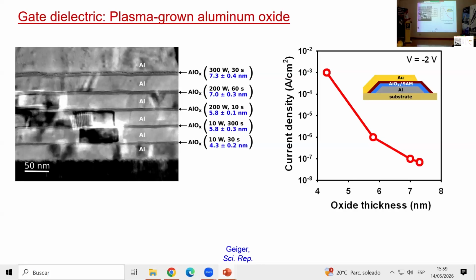That's correct. So what we do is we have to calibrate. So the main parameters for the oxidation process are the plasma power, which we can tune anywhere from 10 watts to 300 watts, and the plasma duration, which we can tune from a few seconds to several minutes, as you can see here, right?